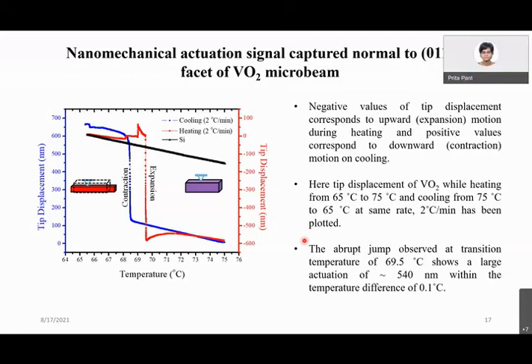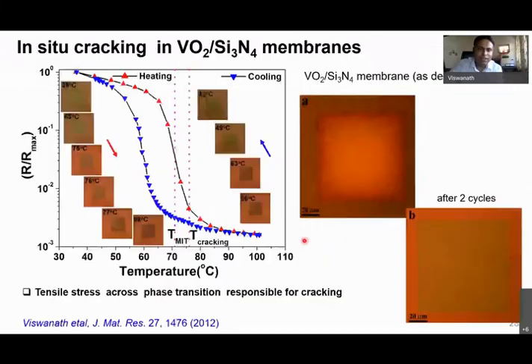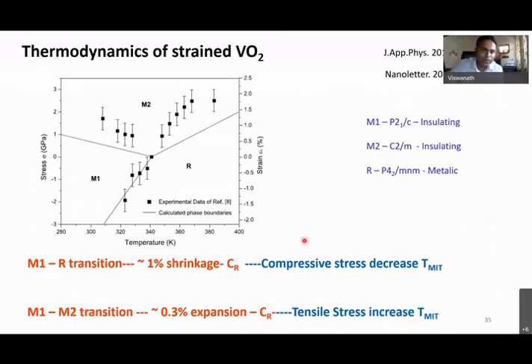No. In fact, initially, we thought by indentation we could locally induce the phase transformation. But at room temperature, when I keep the single crystal, the stress or strain required is much higher. If you look at the phase diagram, it is also shown, going from M1 to R or M1 to M2. If I understand correctly, the minimum required would probably be almost 0.3 to 1 gigapascal.